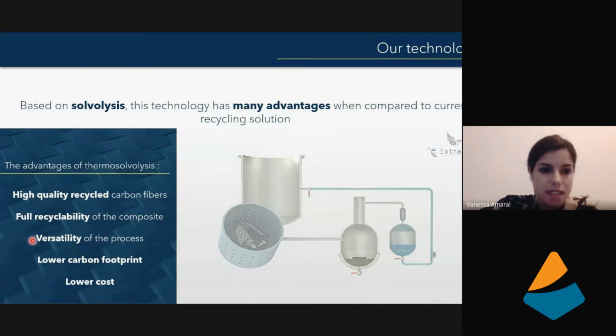So this process has the advantage of not damaging the fiber, so we can recover really high quality material. We have the full recyclability of the composite material, which means we can recover the carbon fibers, but the oligomers as well. And it's a process quite versatile. I'm going to show you later what kind of materials it can degrade. We have a lower carbon footprint as we work at lower temperatures and the chemicals are reused, and it's also a process that has a lower cost.